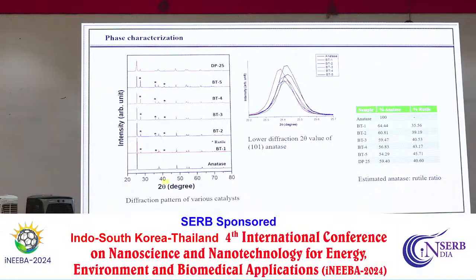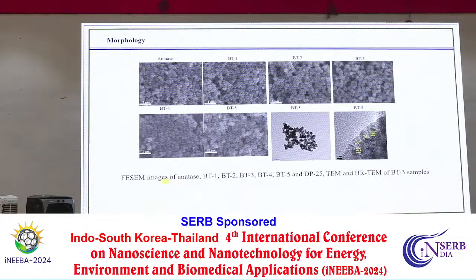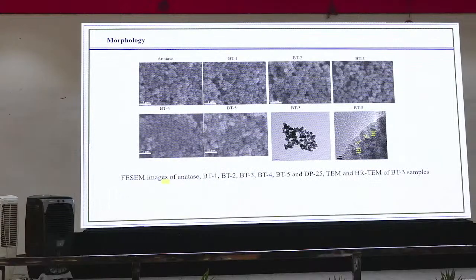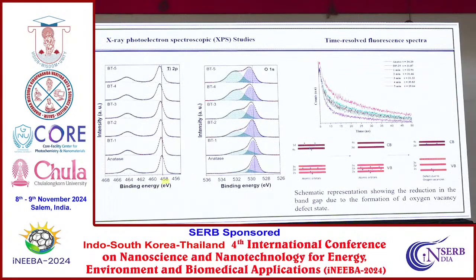Because black TiO2 was in the spotlight at that time. But what turned out for me is that my material didn't work for photocatalysis, and didn't work even for electrocatalysis. However much I tried, I was not getting a better result. I mean, we were not getting a better result. So then, to characterize that, we went for morphological studies and we did XPS studies.